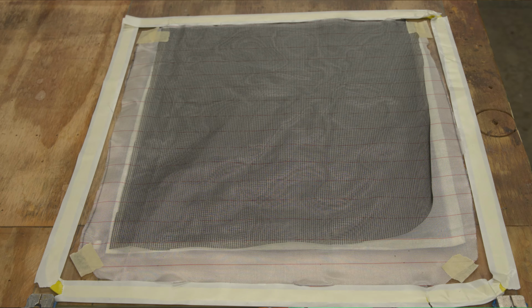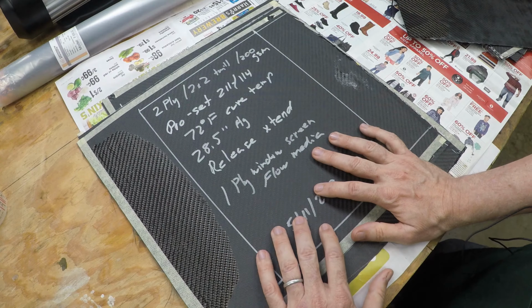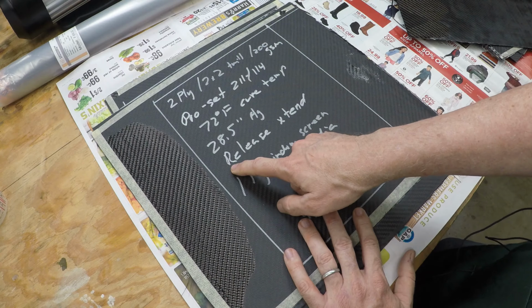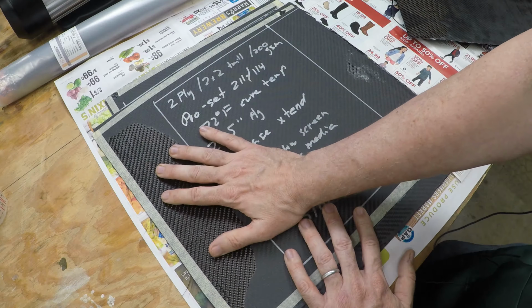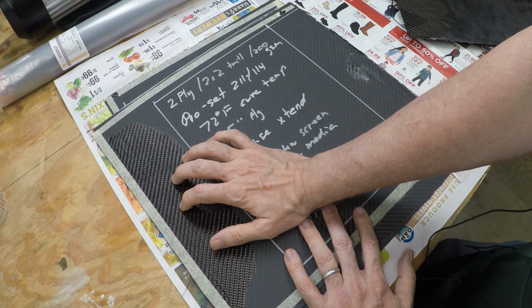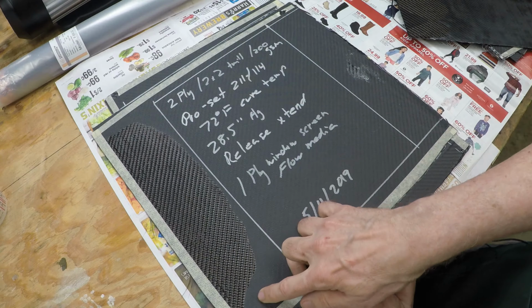And it was 10 thousandths thick. And I thought, well, by golly, that should restrict the resin flow, but still let some go through. So that's what I did. I did another test, except this time for flow media, I put one layer of insect screen in. Just one ply. Resin came in from this side. And you can see, again, I didn't make it to the end of the vacuum side with my resin.